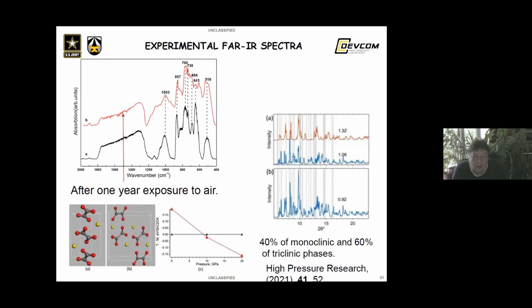After the treatment, samples show practically the same infrared spectra. This is after 1 year exposure to air. And there are some peaks which are specific for poly-CO. We analyzed experimental XRD with strontium oxalate at 10 GPa using the virtual diffraction method and found that a mixture of 40% of monoclinic phase and 60% of triclinic phase provides better agreement with experimental XRD.